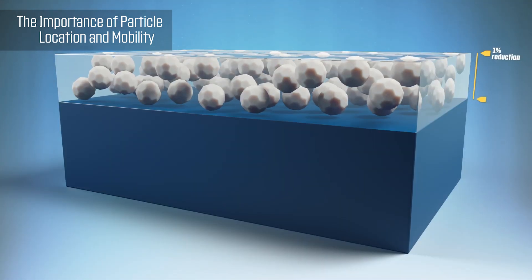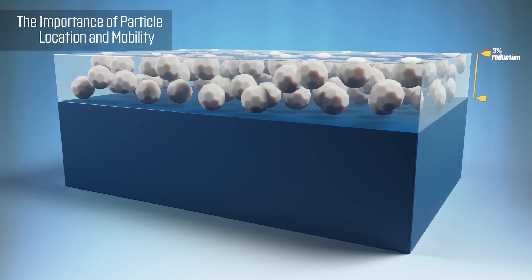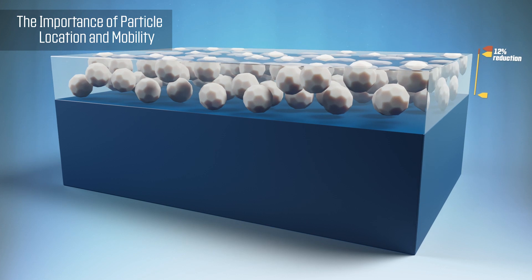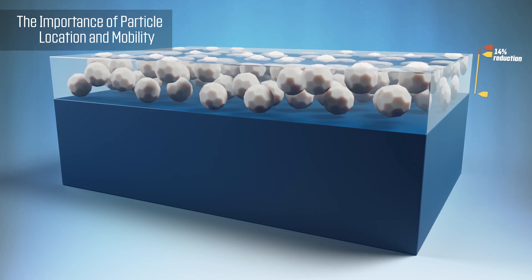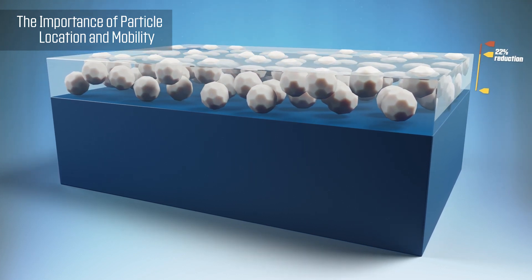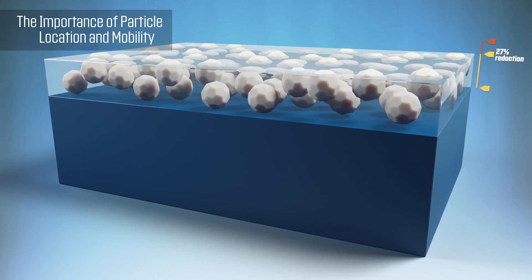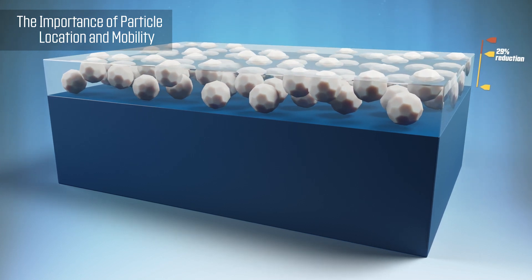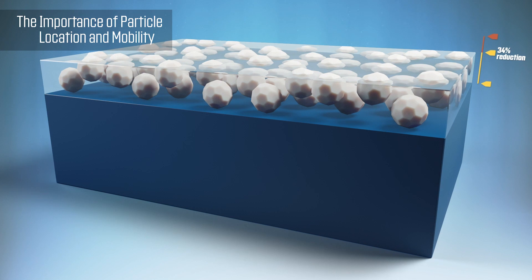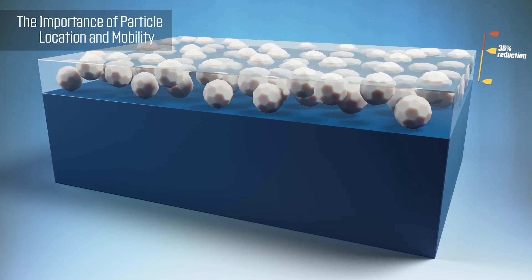Conversely, the ball-bearing effect is typically practiced in solvent-free or UV-cured formulations because short cure times do not enable particle migration to the surface. In this mechanism, particles reach the surface because the particle size of the selected wax additive is slightly larger than the film thickness.